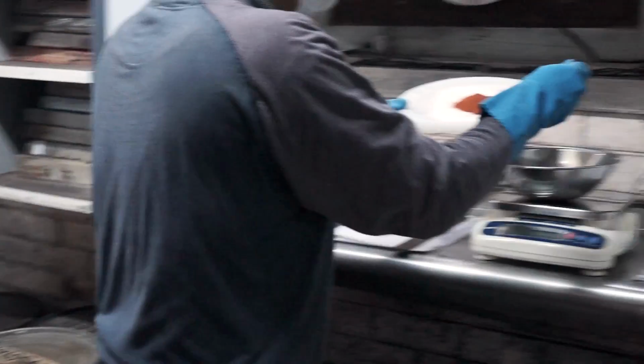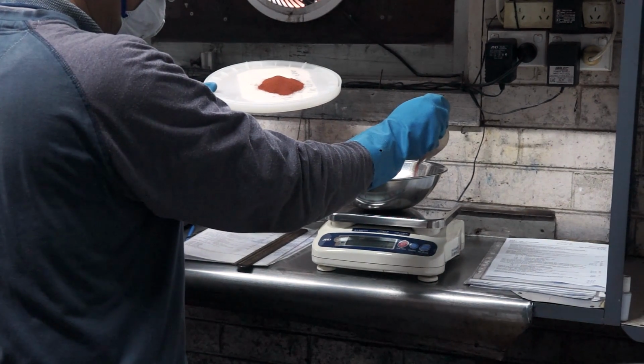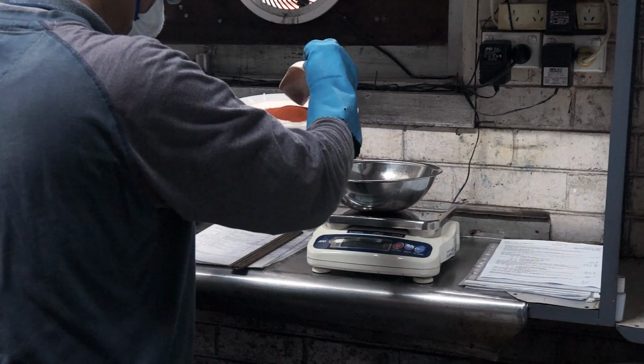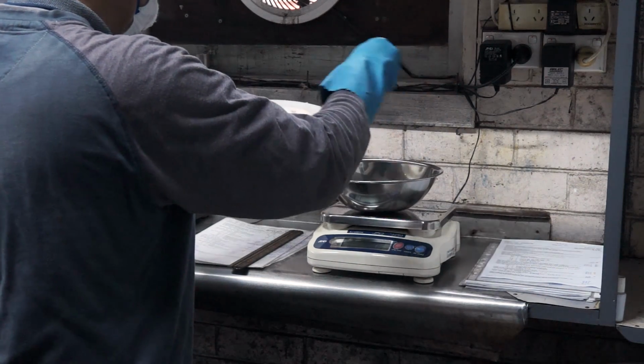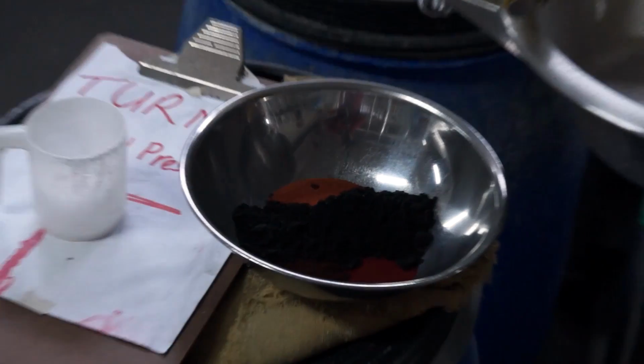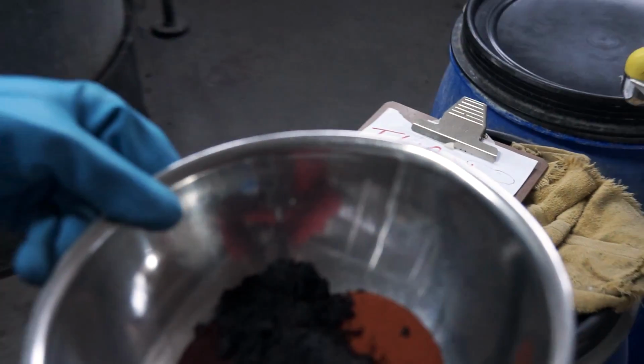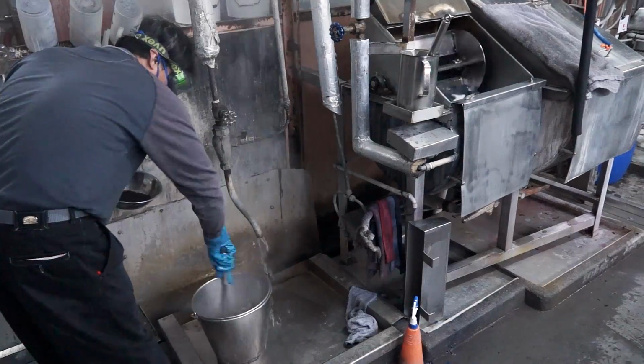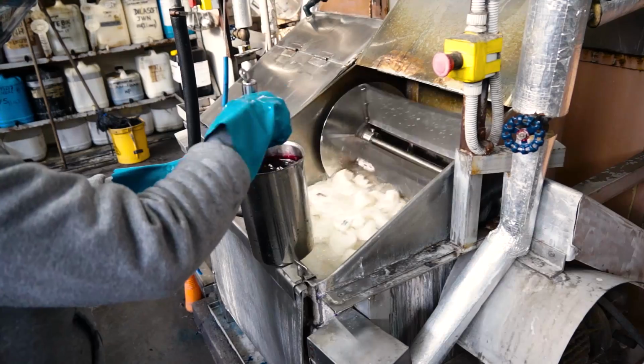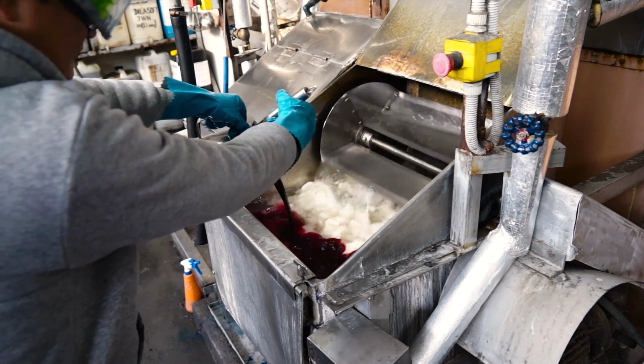We dye all socks in-house, and during this process the yarns relax and the sock contracts to its final size. This relaxation occurs because knitting tensions are removed and the elastomeric stretch yarn contracts to its correct size. This relaxation may be from 10 to 50% depending on the sock yarns used and the length of each stitch. Socks are heated to boiling point during the dyeing process, which means that they will not change shape later when they are machine washed and tumble dried.